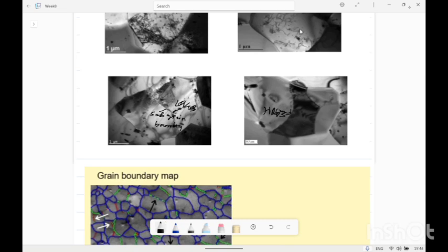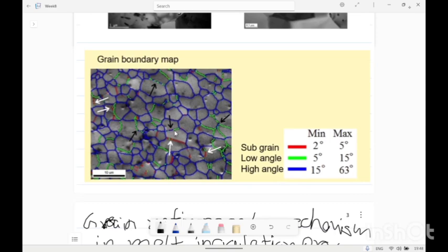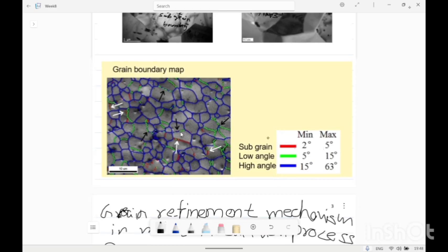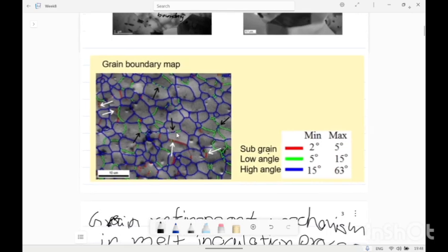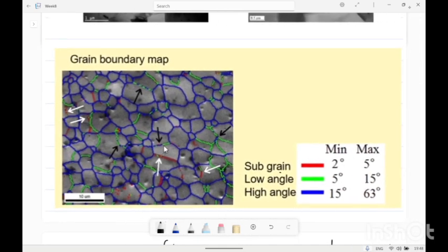So how do the low angle boundaries and high angle grain boundaries form in a microstructure? Here we can see the EBSD micrograph, which is the best tool for finding the high angle grain boundaries, low angle grain boundaries and subgrain boundaries. In this, the grain boundary map is imposed on the image quality map, in which the red lines are denoted by the subgrain, which has a minimum misorientation angle of 2 degrees and maximum up to 5 degrees. The different red boundaries can be seen in this picture. At some point it is converting into the green line or blue line. Blue line is the high angle grain boundaries, whereas the green line is low angle grain boundaries.